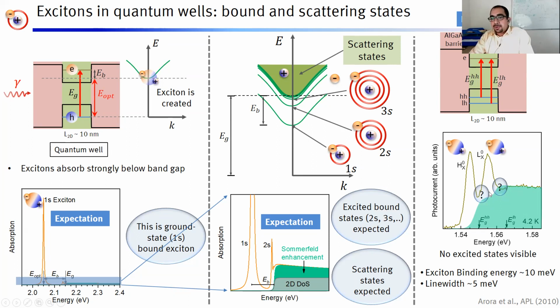However, we are not able to see these excited states of excitons because they are supposed to be, first of all, very small in intensity. Secondly, we have a very broad line here compared to the binding energy. The reason is the binding energy is of the order of 10 meV. So you should see all these states within 10 meV. However, the line width itself is 5 meV. And the intensity is also small. So you do not see very easily all these excited states in a quantum well. Therefore, we have to look for some better materials to study such kind of two-dimensional physics.